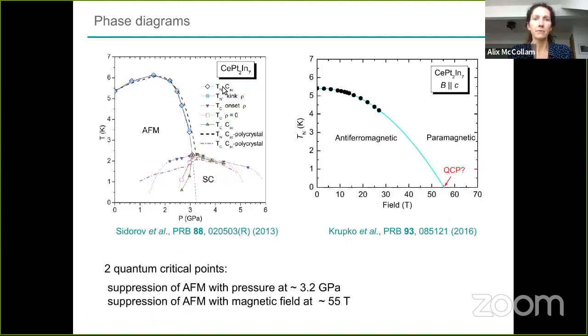Okay, so the phase diagrams of cerium platinum-2 indium-7 look a little bit like this. This is temperature as a function of pressure, and this one here is temperature as a function of magnetic field. With pressure, as I said, first the antiferromagnetism is enhanced slightly, and then you can suppress it, and then superconductivity develops around the region of 3 gigapascals. This is from a series of different measurements, transport, susceptibility, all shown on this phase diagram. As a function of magnetic field, again, you suppress the antiferromagnetism.